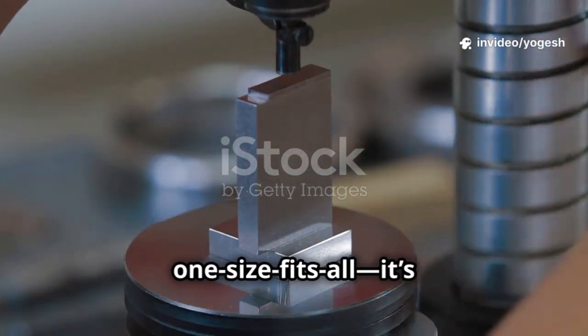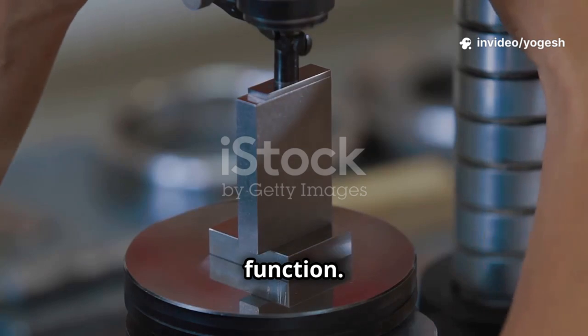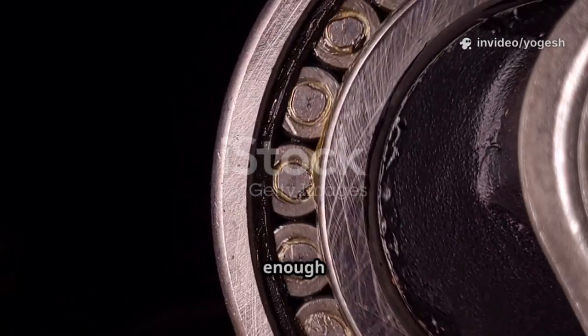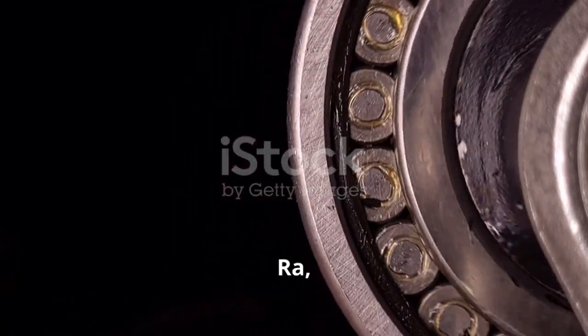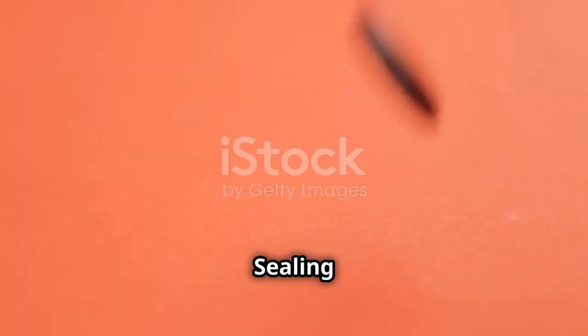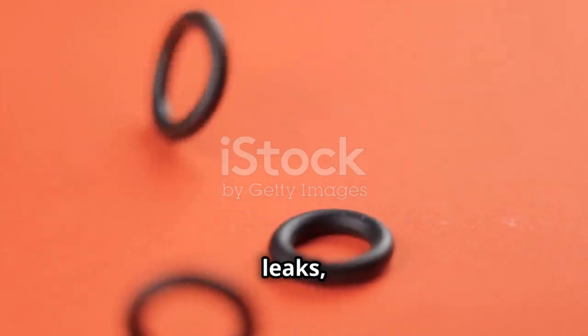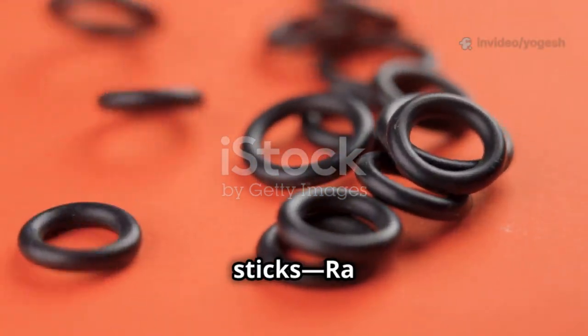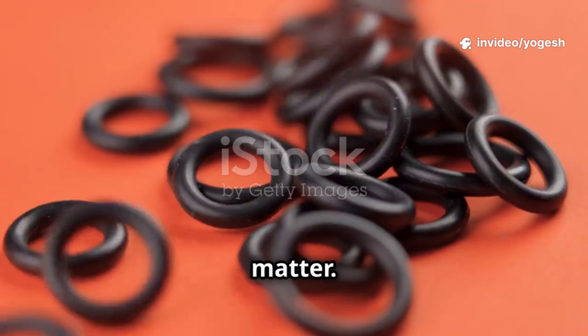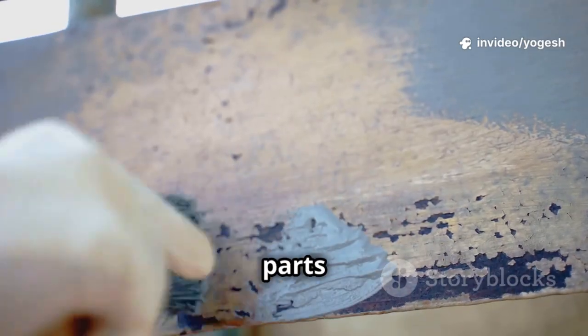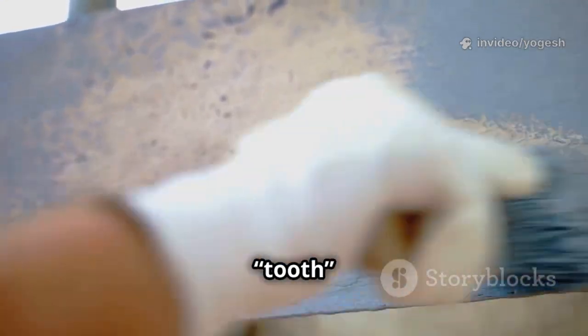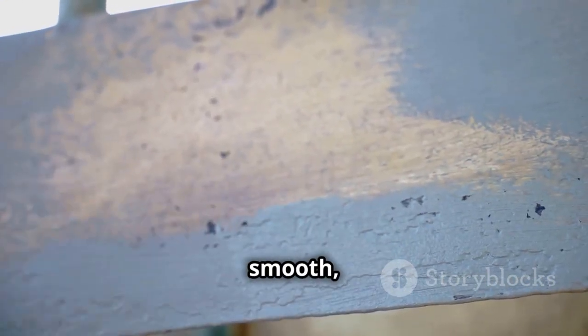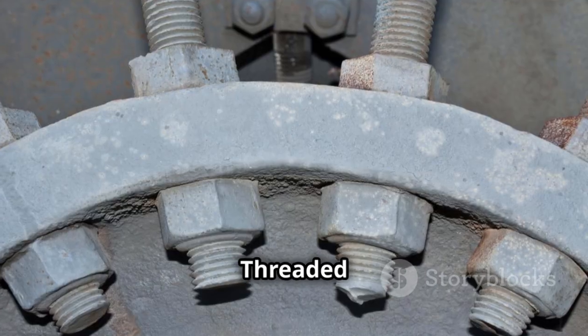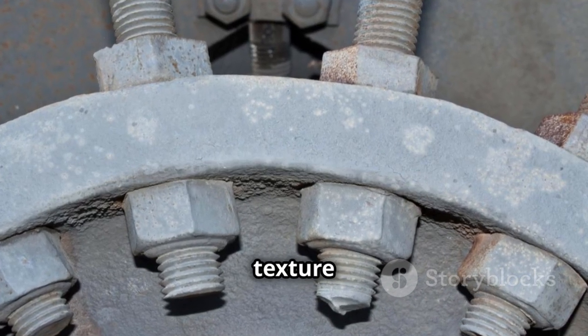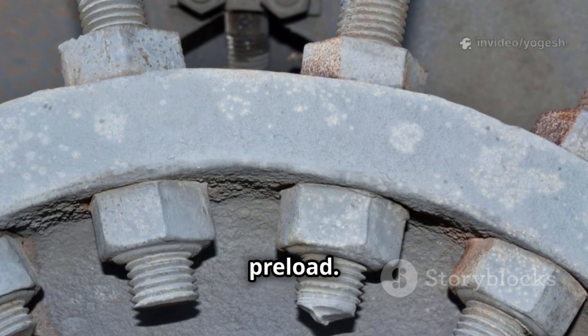Surface texture isn't one size fits all, it's about function. Bearings need a smooth surface with enough valleys for oil, low Ra, negative Rsk. Sealing faces must be smooth enough to prevent leaks, but not so smooth the seal sticks. Ra and lay matter. Painted or coated parts need a roughness that gives tooth for adhesion. Too smooth and coatings peel. Threaded fasteners rely on controlled texture for consistent friction and preload.